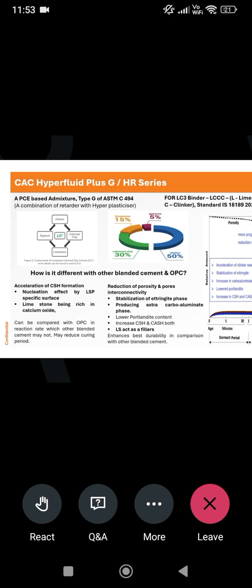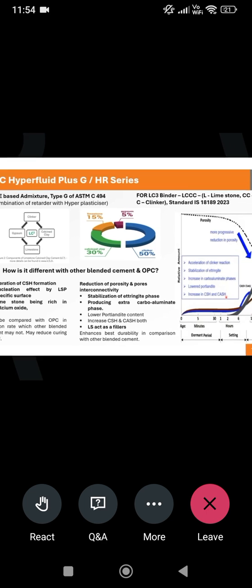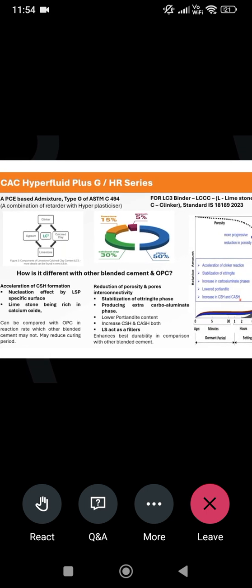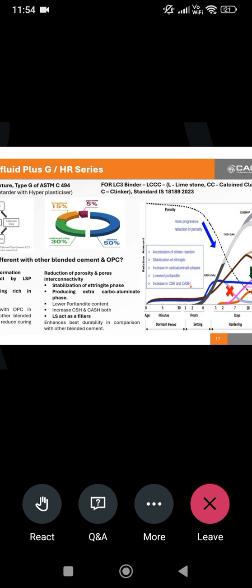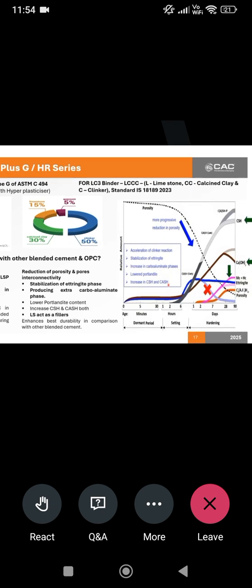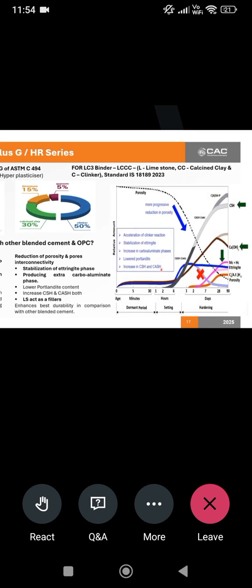It is happening with all cements, OPC, composite, PSC, PPC. But in case of LC3, it is not happening. So this excess alumina, which is supposed to react with this material, is not going to destabilize the ettringite. It is attracted to the carbonate part of the limestone and forms monocarboaluminate and hemicarboaluminate. This alumina is being used with carbonate and producing another hydration product which was not produced in any of the cement. What does it mean? It means that a lot of additional hydration product, apart from CSH, CASH, is being produced in LC3.